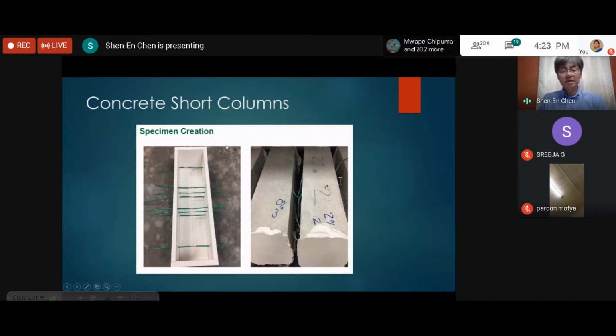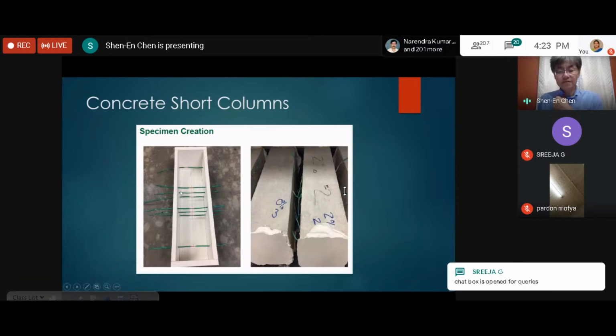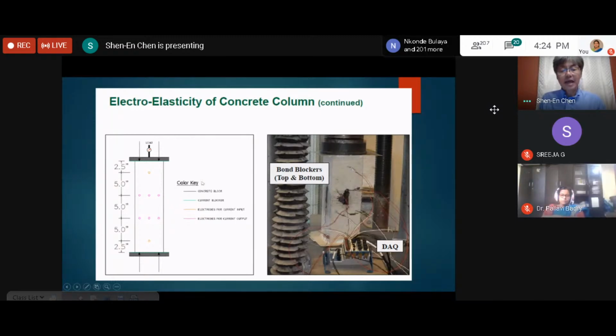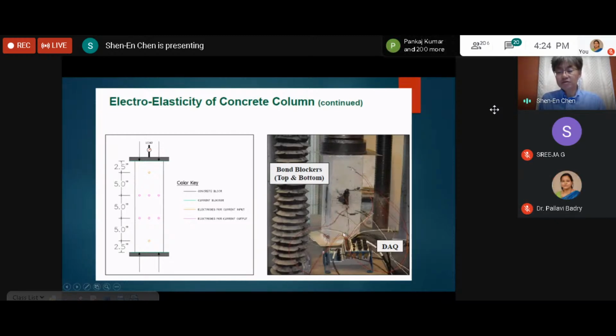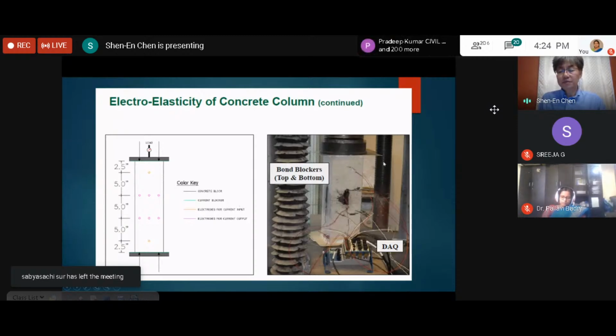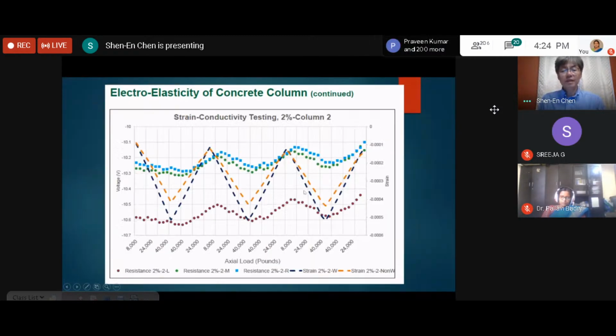And then we start developing concrete short columns. And this is, again, the standard setup of using those conducting elements, the sensing wires. So the self-sensing component consists of 2 parts. One is the fibers that we add into the materials, and the second is the sensor itself, which are those copper wires built into the material. And we did axial testing, and this is our test setup. So these are voltage readers. We measure the voltage change throughout the system, with the current introduced into one of the ends. And this is the measurement.